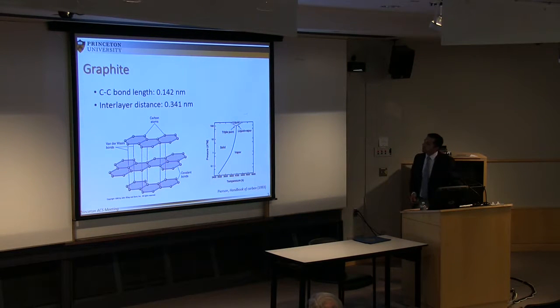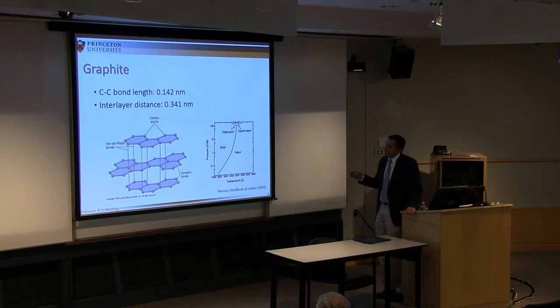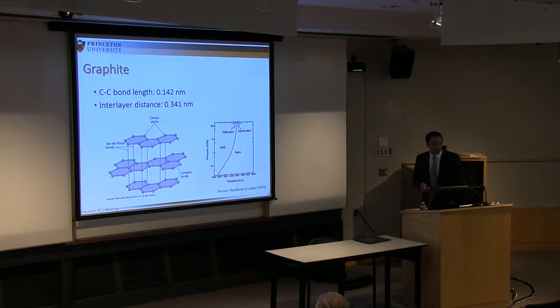So let's talk a bit about the structure of graphite. Graphite has this hexagonal honeycomb structure. Each of these planes is one graphene layer. You have covalent bonds between the different carbon atoms here, and the bond length is roughly 1.4 angstrom, so 0.14 nanometers. And the distance between the planes in the z direction is about 0.3 nanometers. So keep that number in mind, because we will use it later.